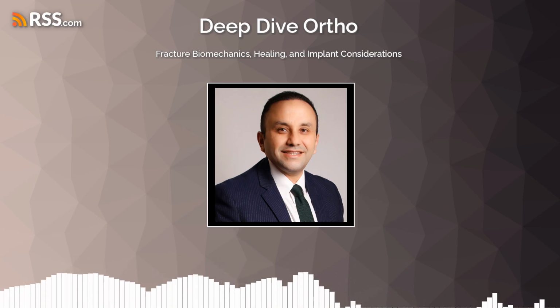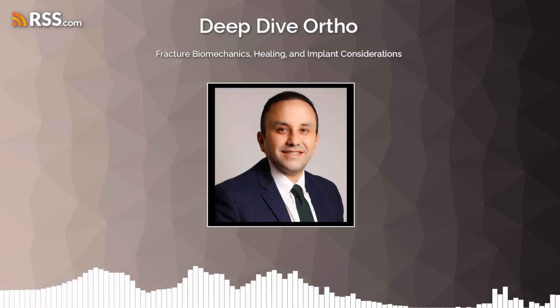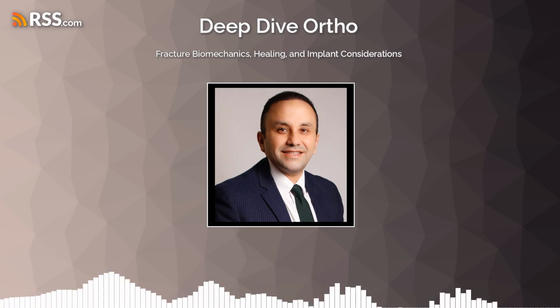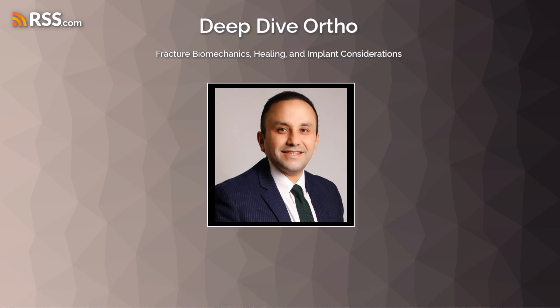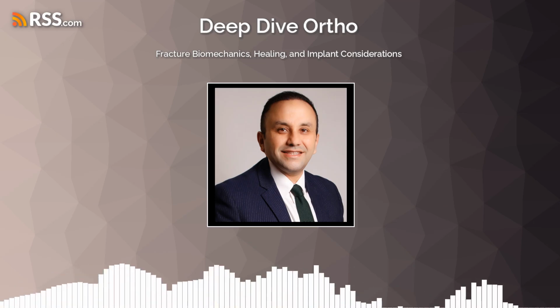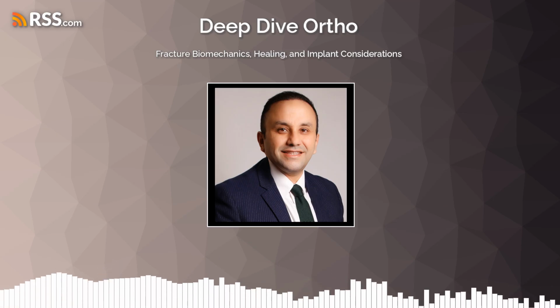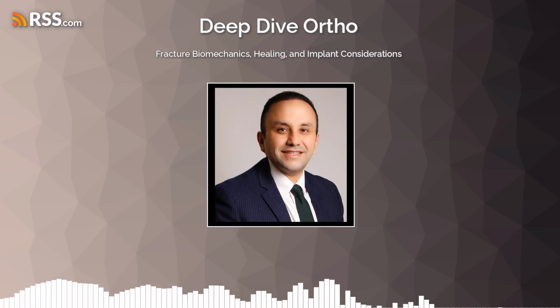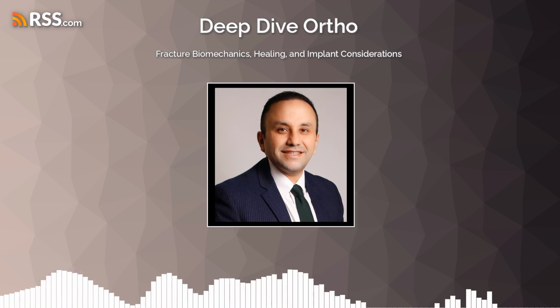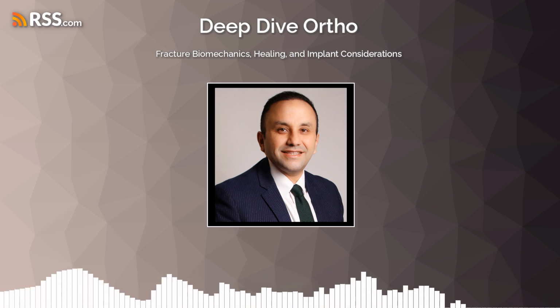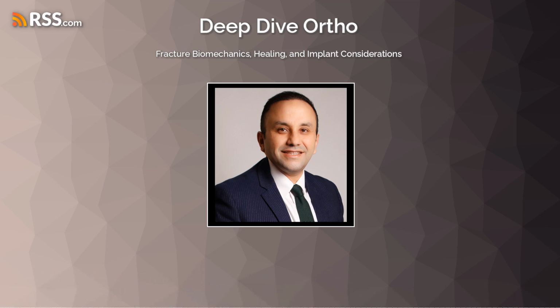There's even a fascinating dose-response relationship noted in the sources regarding direct electrical current. Too little current, say less than 5 microamps, seems to have little effect. A certain range, roughly 5 to 20 microamps, appears to promote bone formation, but too much current, over 20 microamps, can actually cause tissue damage or necrosis. So getting the dose right is critical.